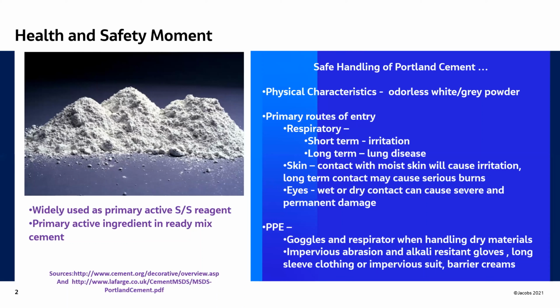And so what I want to draw your attention to here this morning is some of the hazards associated with cement, which is central to my talk today. So cements, Portland cement specifically, is used as a stabilization solidification reagent in many applications. It's used commercially for making concrete, cement block, other solidified materials. And so it's the primary active ingredient in that mix that gets you to pH 12.5 or 13, where the cement reactions are initiated and you begin creating calcium silicate hydrate minerals and others that develop the strength and lead to the metals immobilization.